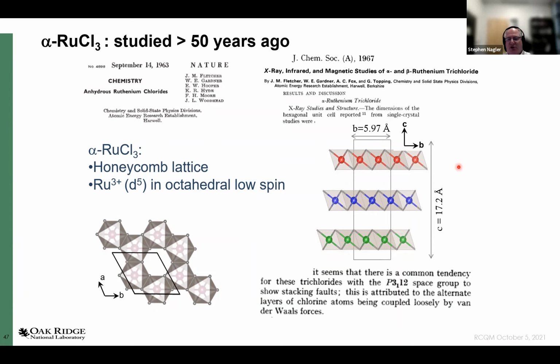And apparently at the same time, the group at University of Toronto was also thinking along the same lines. But I will say, we certainly thought of this without knowing anything about that. When we got a hold of some of the material with the intent to make single crystals, we found that what we had was basically a very small amount of ruthenium trichloride and a lot of other stuff, even though it was sold as 2N pure or whatever. Now, the reason for that was this material that was studied a long time ago was used as a catalyst. And if you have a material used as a catalyst, it doesn't have to be terribly pure. So at that point, this is already, I think, 2013 or even 2012, when we first started trying to do this, we just bought this junk.